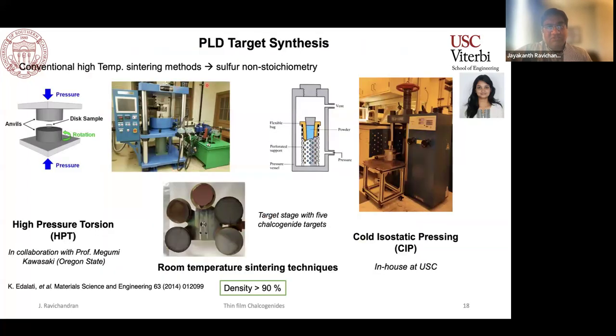Our first challenge was to get nice, dense polycrystalline targets for the thin film growth itself. There were a few different approaches that we tried. We tried the high temperature hot pressing technique, which was not super successful, presumably because it's done in a reducing environment, which leads to some side reactions and non-stoichiometry after we process it.